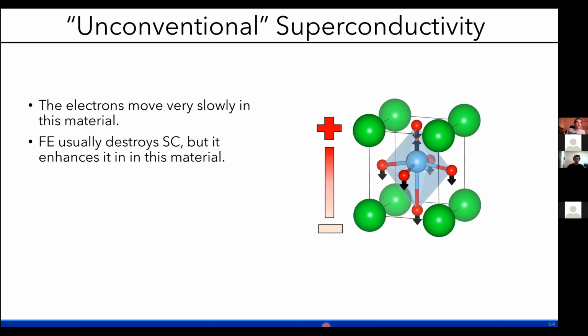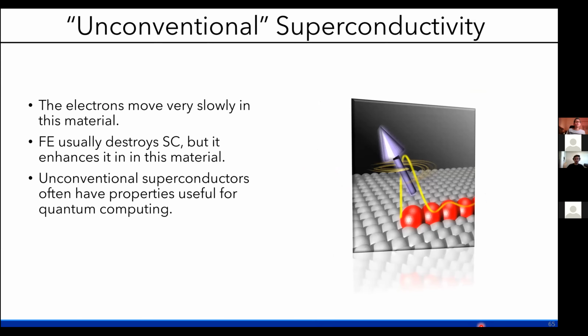Another interesting thing is that ferroelectricity, so this polarization across the material, usually prevents the conduction electrons from flowing. So it usually destroys superconductivity. But in this material, in the ferroelectric state, the superconductivity is actually enhanced. And this is really highly unusual. And we want to understand why this is. And one of the reasons we care about this is that unconventional superconductors often have properties that can be useful for quantum computing. And the details of the reasons behind that are a little bit more complicated than what I want to get into, but that's kind of the motivation for studying this behavior.